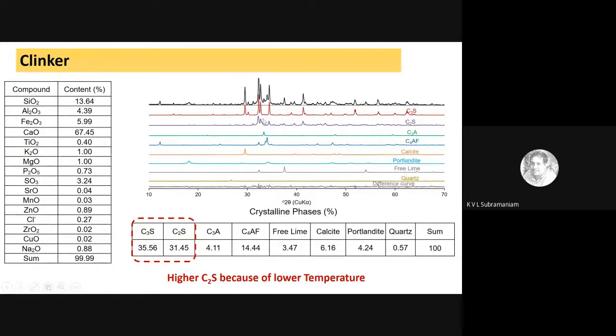So you see that each one of them has a distinct signature in the form of peaks in the XRD signature. And from our characterization, we were able to find that our cement had about 35% of C3S and about 31% of C2S. Now, normal cements will have close to 50% of C3S. We were not able to produce that high level of C3S, but C2S was a little higher than normal cements, because in normal OPC, we have about 25% of C2S. But we were now able to produce cements which had calcium silicates.